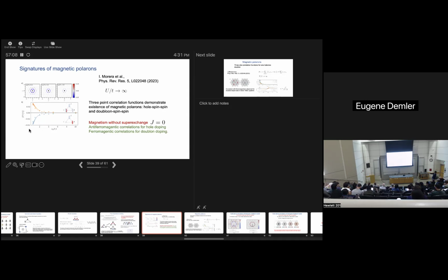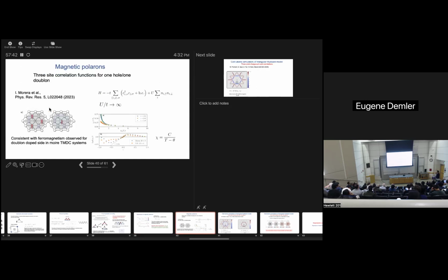And indeed, if you do theoretical calculations, you find that if we look at this three-point correlation function, which we discussed in the case of the quantum gas microscope, it's the dopant, which is either a hole or a doublon, times spins. In the case of holes, they develop antiferromagnetic correlations. Notice the very high energy scale. It's set by the tunneling. That's when the exchange is equal to zero. And in the case of doublons, we see ferromagnetic correlations.